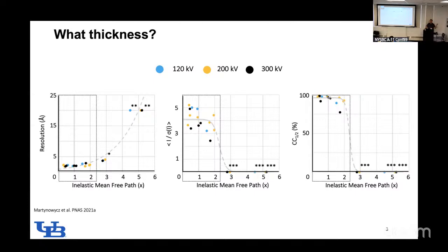What does this mean practically? Your crystal should be less than 600 nanometers. You can go thicker, you can go thinner. Of course, when you have a FIB mill, you can control this. So I always say just aim for 300 nanometers.